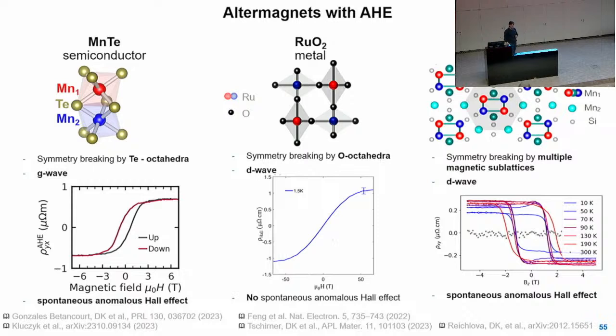No, they won't. This is super individual, depending on what operation links these two sublattices. In this case, that's why I also show it in 2D, you can imagine just rotating it by 90 degrees, changing the color, and you are back at the original picture. So in this case, it's a normal rotation axis. The only statement which is made is that between these two you cannot have an inversion symmetry. That's also one of the reasons why this was missed so long. This is not that people are stupid, but in these magnetic symmetries, people typically blank out the non-magnetic atoms. And now if you remove the black dots here, then all this interesting physics is gone.